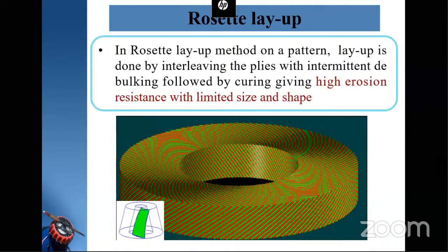This is another important layup technique called the rosette layup technique. In this, we are able to make the component with different hand layup techniques only. But here you can see the outer layer of the fiber is inside. A cylindrical or conical component we can make by using this technique. The layer of fiber is positioned in such a way that one edge of the fiber is at the inside diameter of the component and the other edge is on the outside edge of the cone.